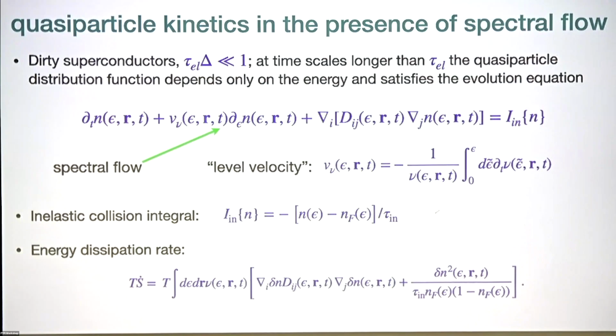Okay, so how do we quantitatively describe this dissipation mechanism? So here the evolution equation, the kinetic equation for these quasi-particles essentially represents the diffusion equation. So now I want to stick to dirty superconductors. Tau elastic delta is small. It's a diffusive regime. And then at frequencies smaller than the elastic relaxation rate, the evolution of these quasi-particles is diffusive. The distribution over momenta randomizes quickly. And then locally, the distribution function depends only on the energy. And the evolution equation is the diffusion equation, but with two extra terms. One is the inelastic collision integral, which we treat in the relaxation time approximation.